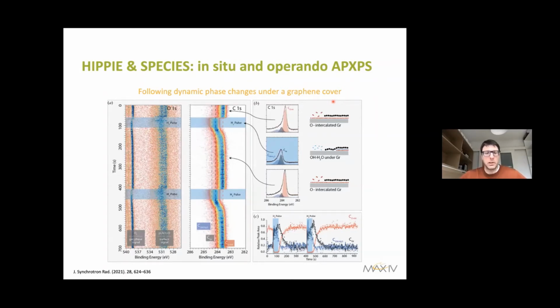So on the left-hand side, you can see a series of oxygen and carbon spectra, depicting in carbon in particular the shifts in the graphene C1s level that are very sensitive to the underlying interface, let's say, if it's pure iridium or some gas intercalated, and depending on the gas, the shifts are different. So in this case, graphene is a kind of probe of what's going on under it.